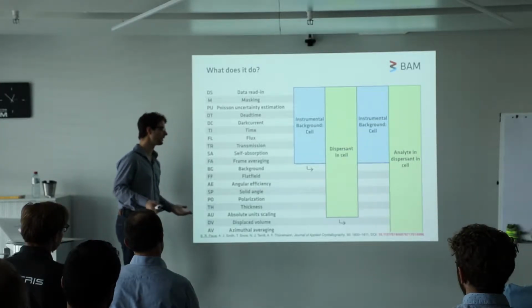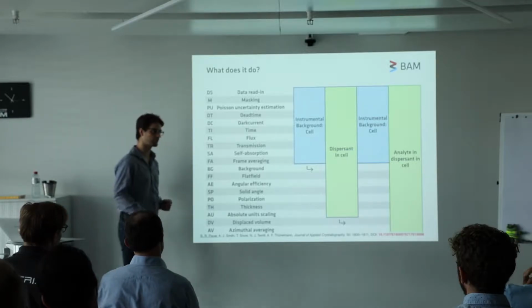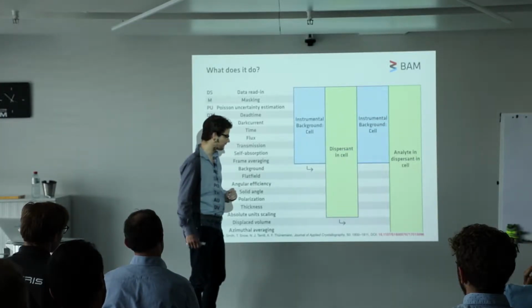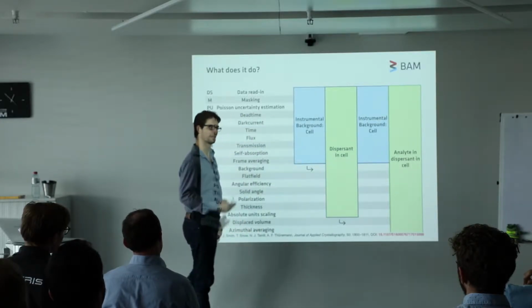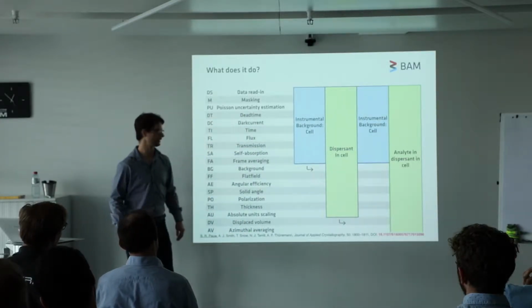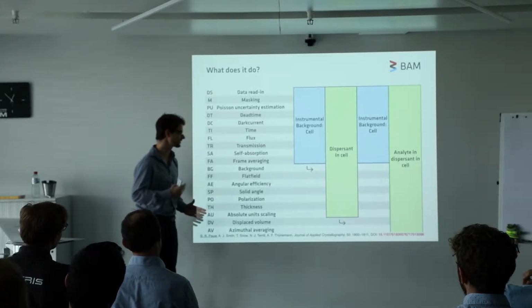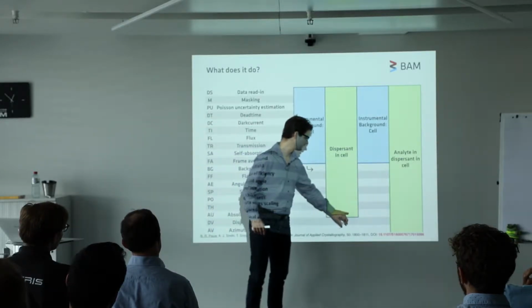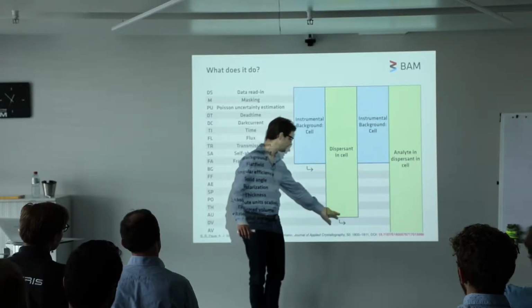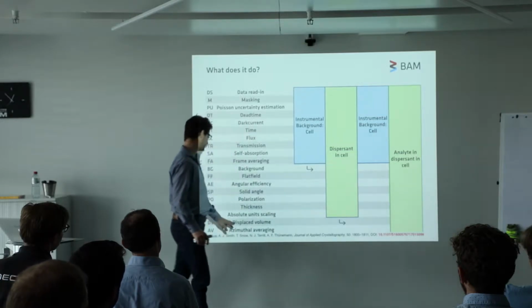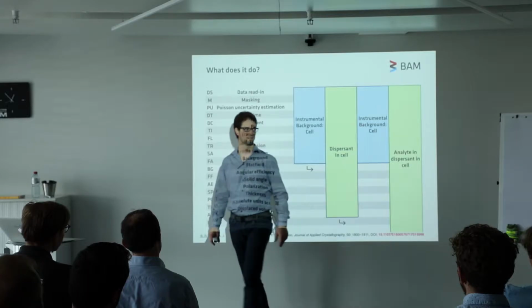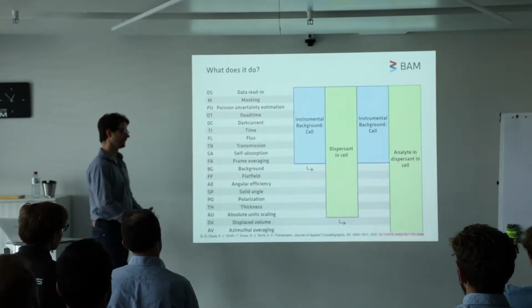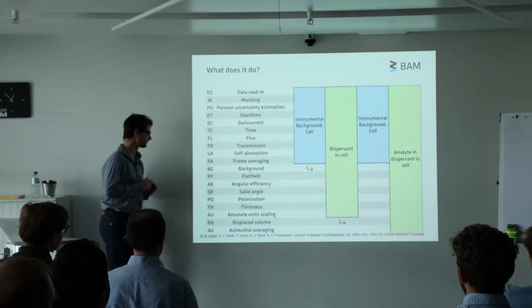If I use chloroform as a dispersant, then I now have that chloroform signal. I can store it in a library and use it later when I have a sample in chloroform. That means I don't need to measure them every single time that I have this particular dispersant. Now, at the very end, you then correct your dispersant for the displaced volume of your sample, and you subtract it from your analyte, and then you have your analyte over there in absolute units and with uncertainties.